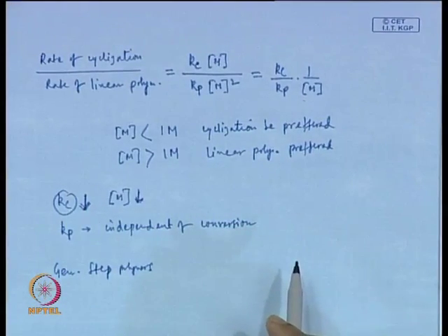Now, what is the problem if I have a few cyclic molecules in the polymer at the end of the polymerization? First of all, we have seen that the presence of these small molecular cyclics will increase the polydispersity index, which means the distribution of the polymer chains, and this affects properties in several cases.